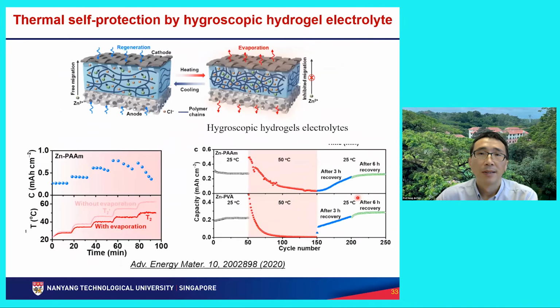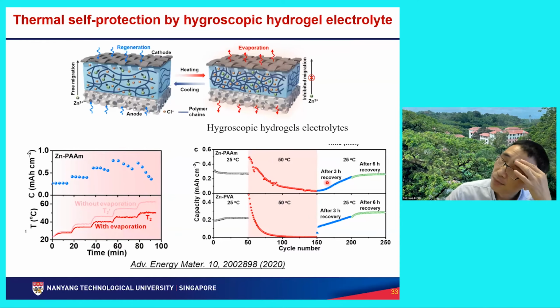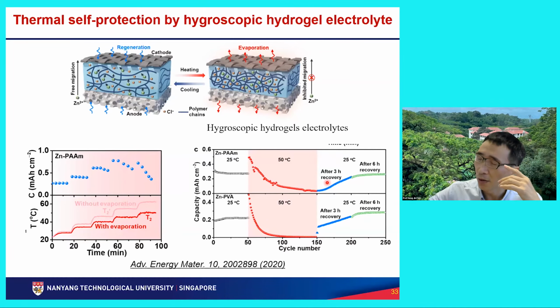And thermal management. We don't want a battery to get too hot, right? Although current lithium batteries can work quite hot, sometimes you touch a mobile phone, especially if you put it outside in the sunshine, and you feel the battery is very hot. Or if you watch videos, watch NBA, it gets too hot. The battery usually can work within a wide temperature range, a lithium battery, let's say minus 20 to 60 degrees. But if it gets too hot, then it can catch fire, as I mentioned at the beginning.